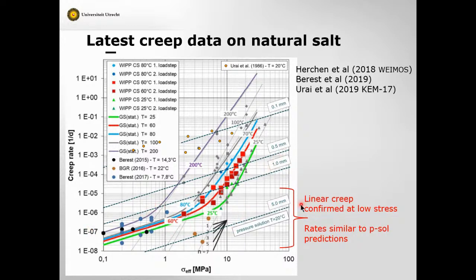And here are the predictions from our pressure solution model derived from fine-grained experiments. So we measured the data up here. These are our data here, and extrapolate that using a theoretical law to a grain size of 5 millimeters and 1 millimeter, and you see it's definitely in the right order of magnitude for the behavior observed in these incredibly long-term creep experiments by these guys. So, of course, we were very, very pleased to see these experimental results on natural salt with this coarse grain size coming pretty close to what we predicted.